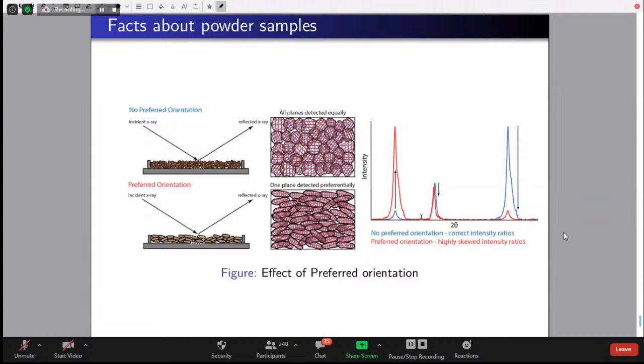Because, sir, the pores which are existing inside the material are not going to contribute to diffraction. They are just voids. So X-ray diffraction thinks that those are defects, but practically the material itself is a porous material. So we can't get that porosity. Okay, sir.